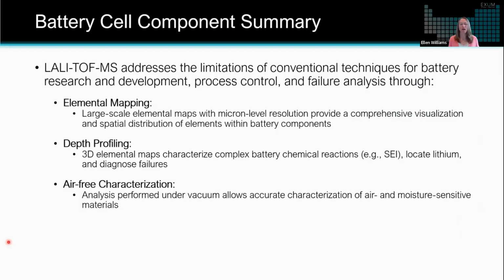And I certainly want to leave some time for questions, so I will just quickly summarize once again, now that we've gone through those battery cell component examples, things on the anode side of things, how this technique helps R&D, process control, failure analysis. We saw the elemental mapping, we saw the depth profiling. One thing we've touched on, but I do want to specifically point out, is that those lithium metal anodes, because they are air sensitive, were analyzed in an air-free way, and that is a big advantage of this technique.